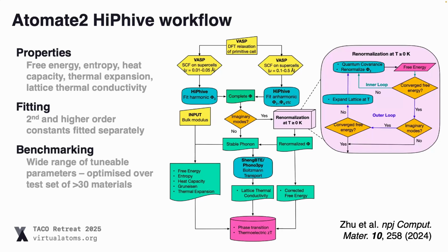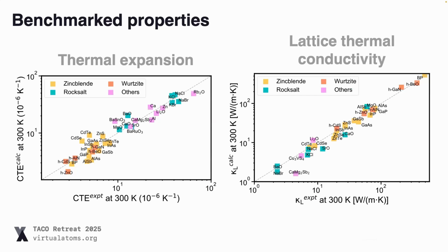So the properties that we can get from this are things like the free energy, entropy, heat capacity, thermal expansion, and lattice thermal conductivity. We are also able to get temperature-dependent phonons. So it's not exactly the self-consistent phonon approximation that we heard yesterday, but it's something related to that. And so here's just an example of some benchmark properties. This is looking at the thermal expansion for a bunch of binary systems, and this is looking at the lattice thermal conductivity. And again, you can see that this is against experiment, and we see pretty reasonable agreement compared to experiment. I mean, there's all the usual caveats here.